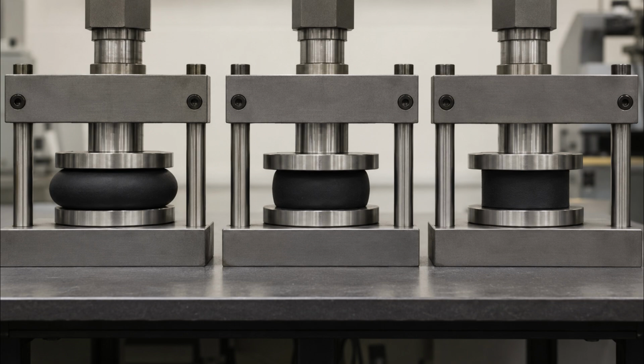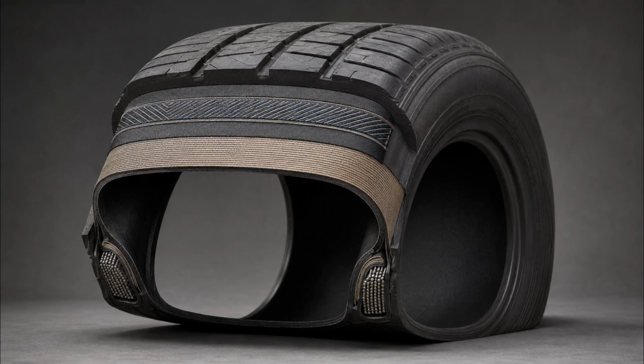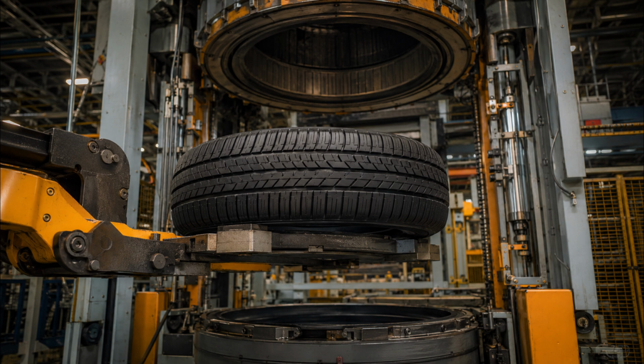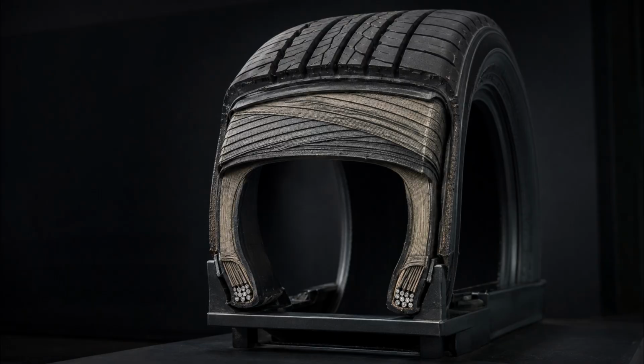The reaction must be controlled through materials of different thicknesses and composition. Time, pressure, temperature, and formulation have to converge. Insufficient curing may leave rubber without its intended properties. An inappropriate cure can also damage performance. The factory is not heating the tire until its exterior merely looks finished. It is controlling a chemical transformation throughout a complex composite structure. Curing does not create the tire's architecture. It makes that architecture permanent.